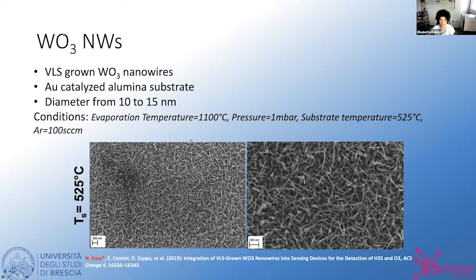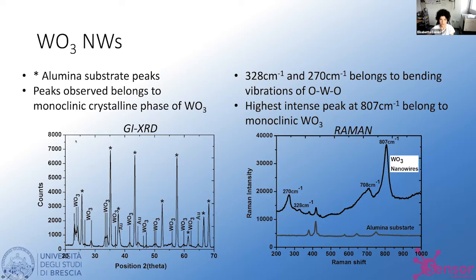We have investigated also tungsten oxide, and here you can see the morphology of tungsten oxide nanowires. You see the diameter is really small, from 10 to 15 nanometers. In this case, we have used a gold-catalyzed alumina substrate, and the temperature of the substrate is around 500 degrees C. And we are having these relatively long and thin nanowires. We have analyzed, of course, the structure and the phase of the tungsten oxide that we have obtained.